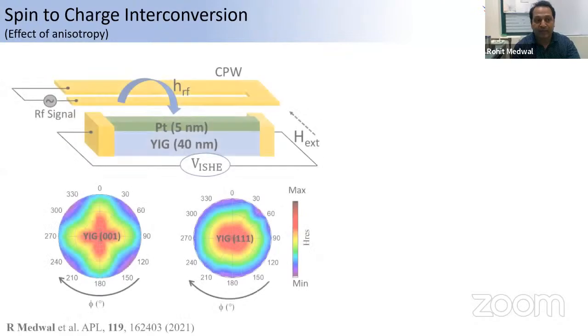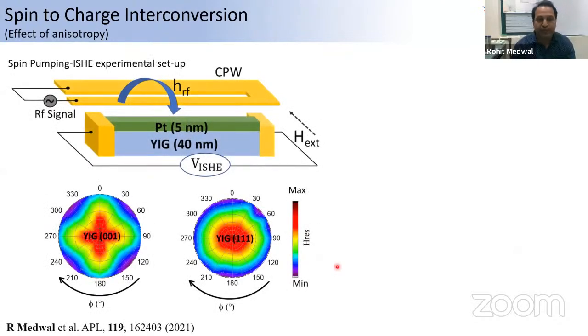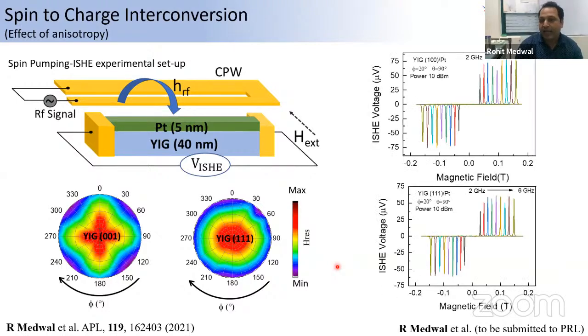And finally, we made the devices out of it. We chose two material systems. One is YIG 001, where we have the perfect cubic anisotropy in the system, and the YIG 111, where we don't have the cubic anisotropy. We made the devices and measured the inverse spin Hall effect signal. That is very common, everybody can do that. That's not interesting, because we have been doing this for almost 10 years, measuring the ISHE voltage in the system. The interesting part is how we can modulate this spin current in the system. This spin current which is being pumped into the platinum mainly depends on two contributions.